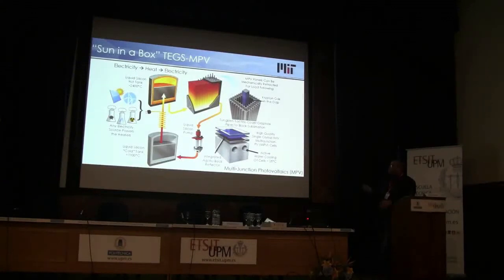So this is the overall schematic of how the system works. We envision, as someone mentioned earlier about the insulation, particularly in this portion of the system, not necessarily over here, but particularly in this portion, filling this with krypton rather than argon, so this will help to cut the heat losses. So we're not envisioning operating this in a vacuum. If you look at this deposition issue of going from hot to cold in a vacuum, it's way too fast. It's like it's a losing proposition. I don't think that there's any way that you can keep even tungsten from coating all over the PV. So we do envision keeping this at 1 atmosphere in a gas environment.